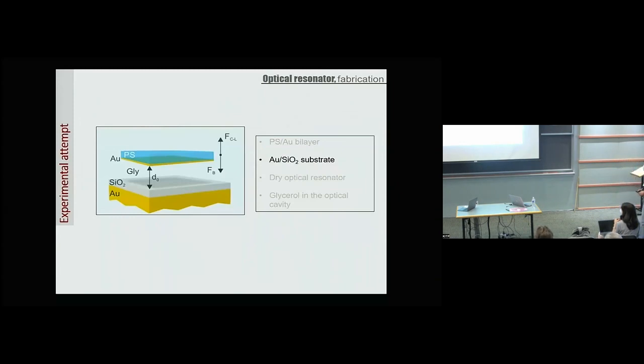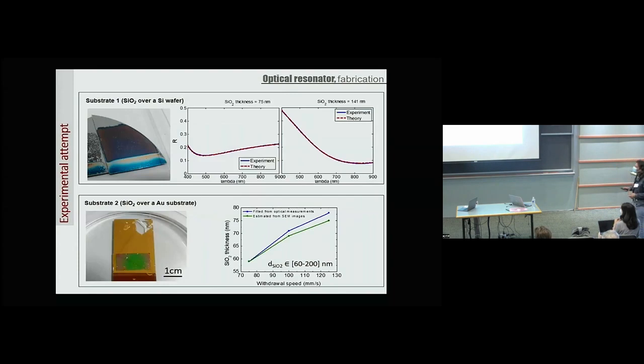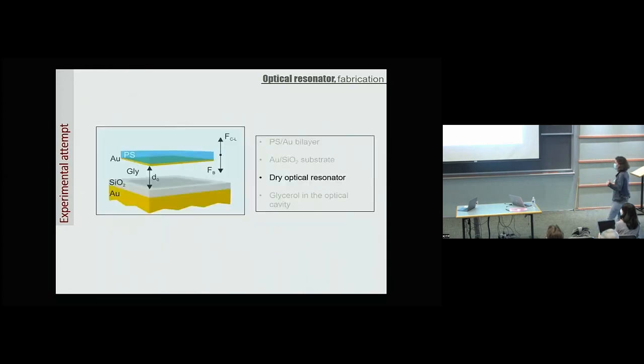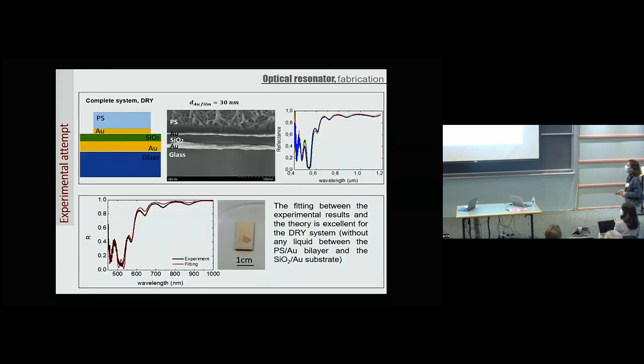Then we went to the fabrication of the substrate, the gold plus the silica substrate. First, we started with a silicon wafer, and we also considered the gold substrate, and again, everything was fine. We could easily grow some thickness between 60 nanometers and 200 nanometers, more or less. Here you can already see an optical cavity. And then we combined everything together without glycerol, so we have an optical resonator in the dry system, with the bilayer on top of the substrate. This is how it looks.